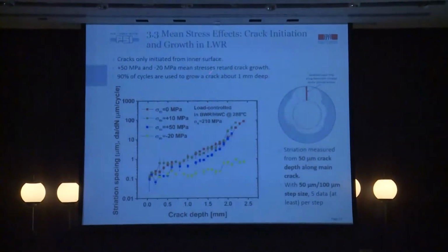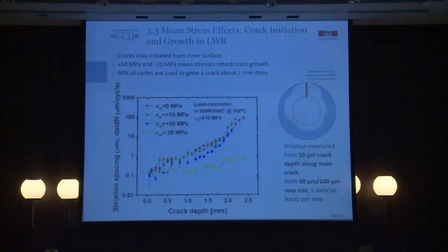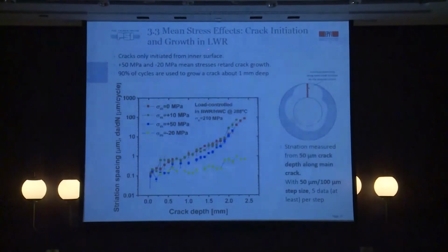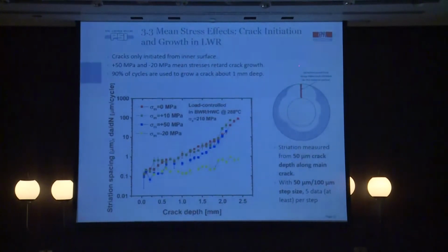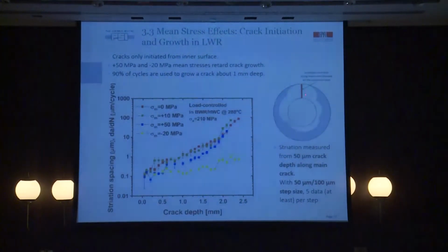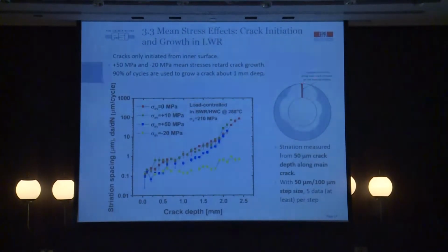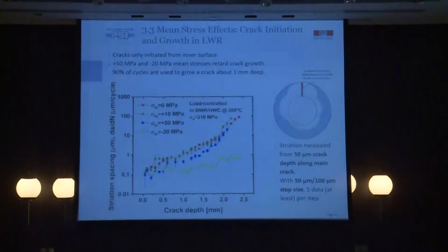And in order to check the mean stress effect on the crack initiation and the crack growth, we measured the striation spacing along the main crack of the fracture surface, and we found the mean stress. These two curves are with positive 50 mean stress and minus 20 MPa mean stress. The mean stress has retarded the crack growth rate.